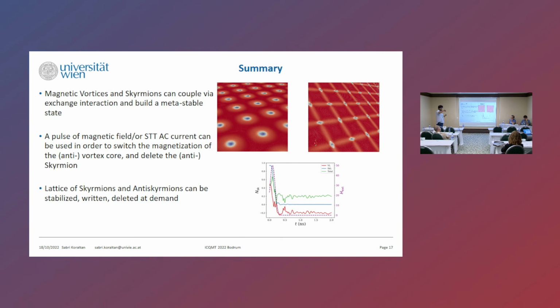But the idea is that in the case of the anti-skyrmions, you can rotate them a bit, right? And then you can apply the current at 45 degrees, and you can get rid of the Hall angle. Because if you apply the current along this direction, you'll have the Hall angle. But if you put your cross at 45 degrees and you apply the current at that 45 degrees, then you don't have a skyrmion Hall angle. So you can propel the anti-skyrmions straight forward.